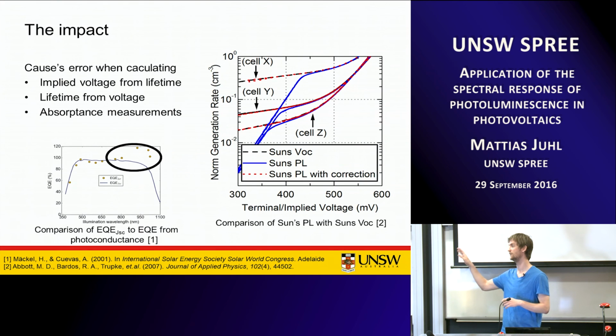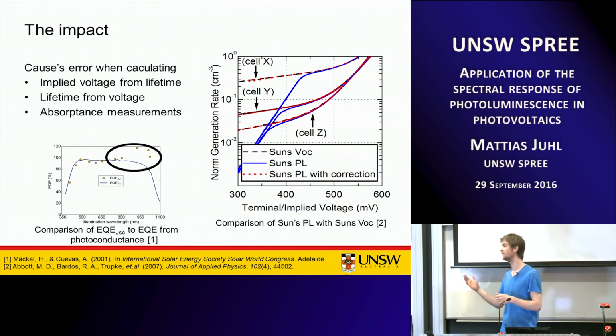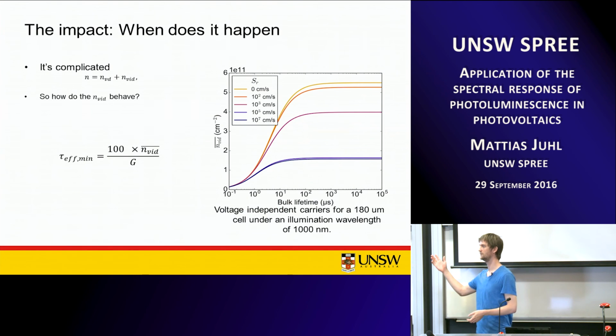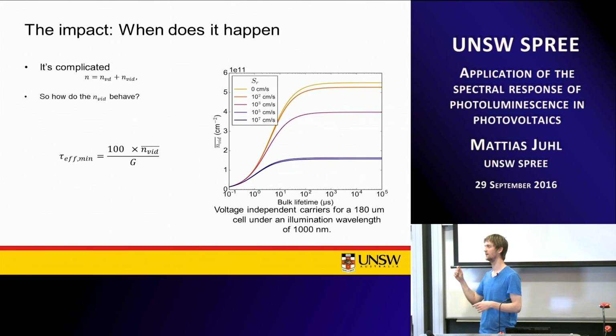This hump is really apparent when you have a bad front surface because it brings down your voltage-dependent carriers. So you can do it, but I think the usefulness for PV in investigating these areas becomes quite hard because we're already at such low surface recombination velocities, with standard screen-printed rears being a couple of hundred. But you could even enhance this by putting the junction voltage to 0, right? You just short circuit the cell, then you know you have 0 carriers at the junction. Yes. Then you only have the independent carriers. And if you have a cell already in line, you know the current and then you can calculate back. So this is roughly what you'll be getting out. If you have bulk lifetimes over a couple of hundred, you won't really be getting out any information. If you have surface recombinations between 200 and 0, or 100 and 0, you're looking at a very small value you're going to be trying to calculate. So you can do it, but I'd question the effort involved for the reward.